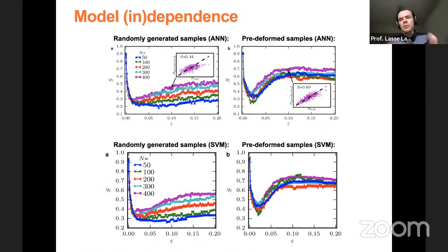Then you can, of course, try to see how dependent these results are on the machine learning model that you applied. Of course we are physicists, not machine learning scientists, so we want results that do not only reflect the properties of a specific machine learning model, but reflect the actual physical system that we study. In the top row are the curves that I just showed you on the previous slide, with the score parameters constrained for the neural network. Then we can do the same with the support vector machine, and you can compare the curves. They are not exactly the same, but they are pretty similar. So the choice of the machine learning model does not really seem to matter that much. It's more the physical system that you look at, I would say.